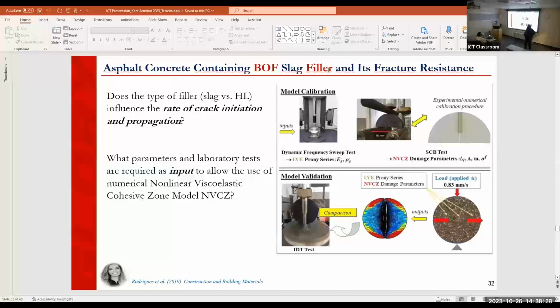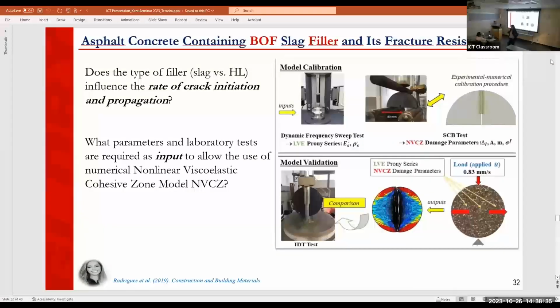Okay, so in this study, we tried to use numerical modeling to infer how the addition of slag was changing some fracture parameters, and each fracture parameter can be associated with how fast the damage is propagating and also when the crack is being initiated. So there are many insights that we can get. This student took two samples. The only difference was the type of filler: one is slag, one hydrated lime.